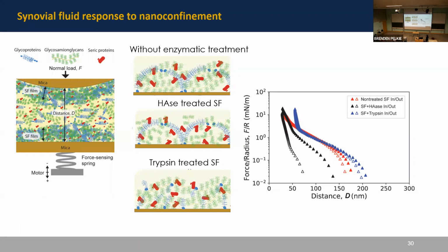So the red curve is the full synovial fluid, and the solid data points are the compression, and the open symbols represent the decompression or the out curves. And we see that for both full synovial fluid and the trypsin treated synovial fluid shown here in blue, there is no hysteresis. However, there's a shorter compression range for the trypsin treated film. But we see a significant hysteresis when the films are treated with hyaluronidase.